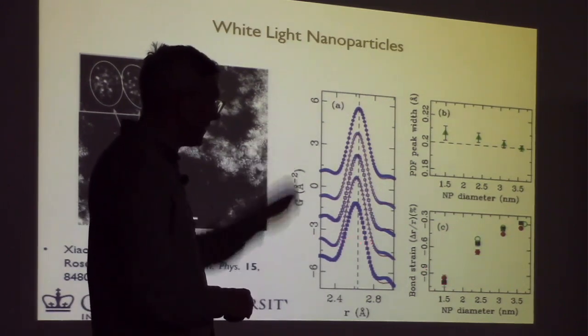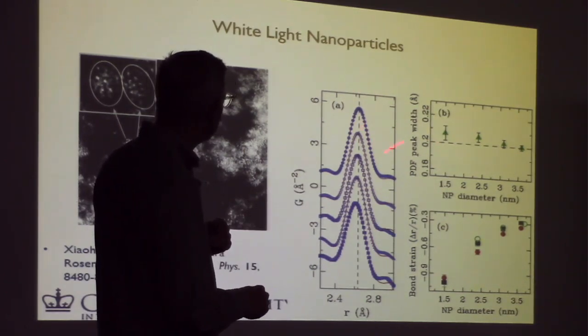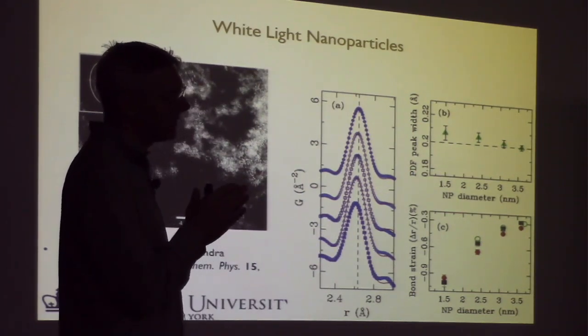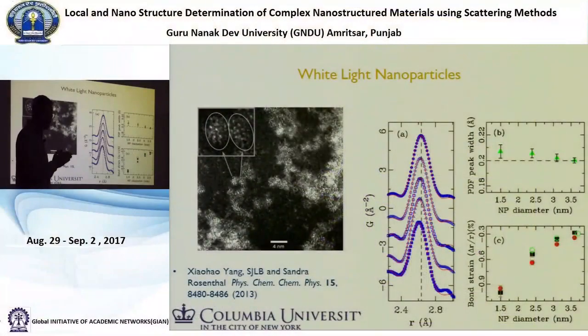And if you look carefully, I told you that the peaks in the PDF don't get broader as the nanoparticle gets smaller. That's not quite true. If you look very, very carefully, you can extract the width of these peaks as a function of nanoparticle size, and it does actually get slightly broader. But this is not a size effect. This is actually coming from the fact that there's a broader distribution of bond lengths in the small nanoparticle.